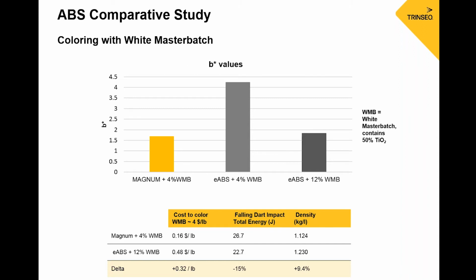One other thing to consider if you need to add more TiO2 is the effect that it will have on the impact, the toughness of the product. You're going to see a decrease. Those TiO2 particles, inorganic particles, are very coarse, and you will see a decrease in the toughness if you need more of that in the product for the aesthetic value. Just in that difference, we could see a 15% drop in the toughness of the product having more of that TiO2 there. So 2% total versus 6% total, we saw a 15% drop.